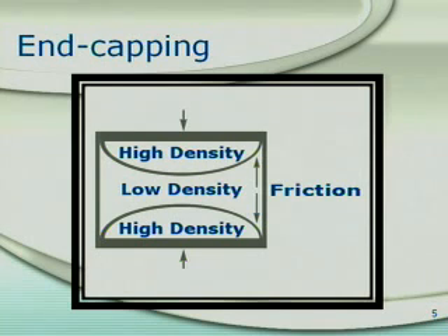Since our goal is to get the highest density possible, but we also need specimens that will survive the entire densification process, studies should be done to find what the most efficient uniaxial pressure is in terms of both density and quality of the pellets. Future work must also be done to optimize the process in the areas of sieving, dispersing, and sintering to get fully dense and transparent ceramics.